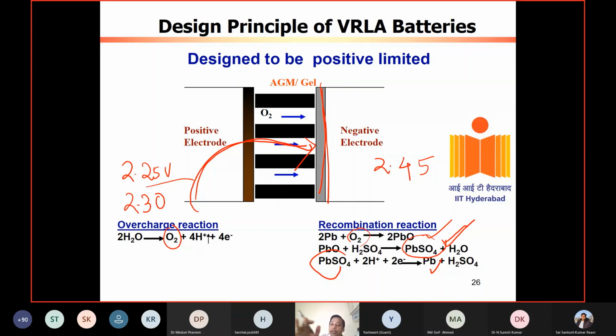In your home, the battery is charged only to 2.3 volts per cell, so you don't go to this one. For some commercial applications, if you go to 2.4 volts, then this hydrogen evolution can be eliminated. So this is based on the oxygen recombination mechanism: the valve regulated lead acid battery. There is a valve also there.